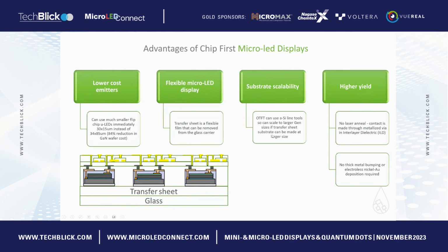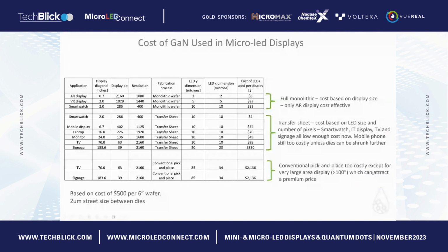We're not using thermal evaporation on a Gen 8.5 line, and we're not using lift-off processes, which generally aren't used for that. We think there could potentially be a much greater yield of the connectivity between the LEDs and the backplane, because we're avoiding these metal bumping processes. We do require some bonding between gold and the LEDs, but because it's through a sputtered via and not through a eutectic bond, we don't need to make these thick bumps on the backplane.